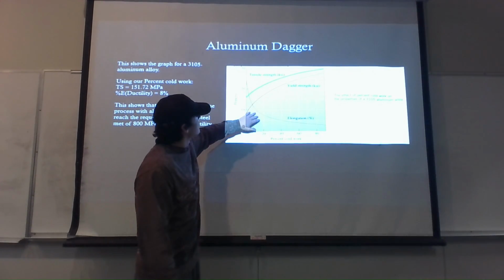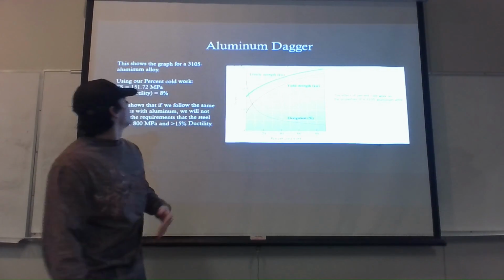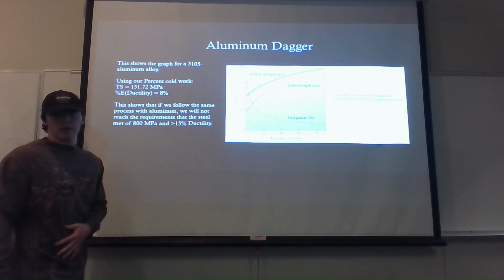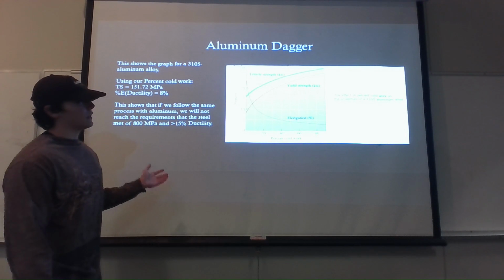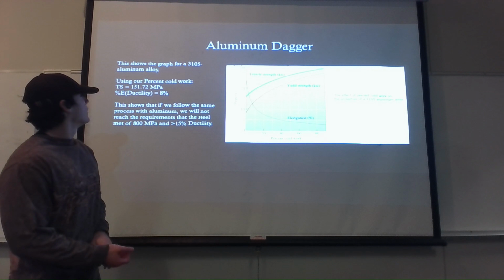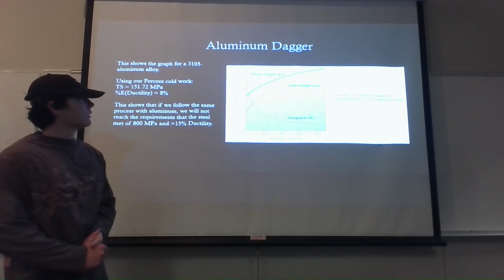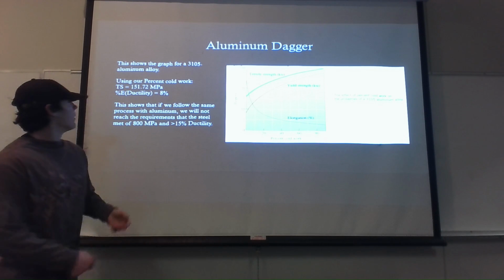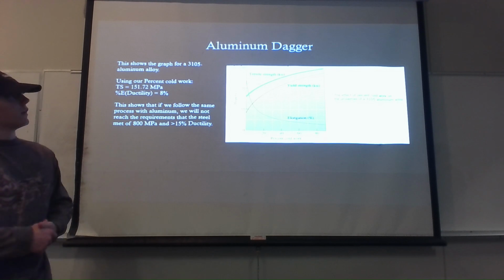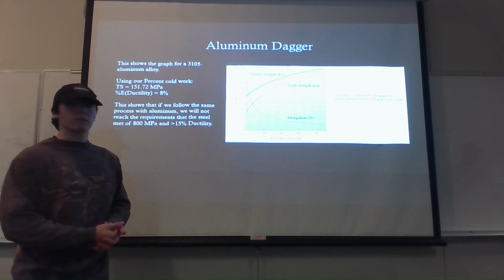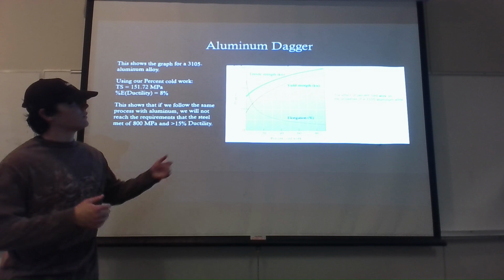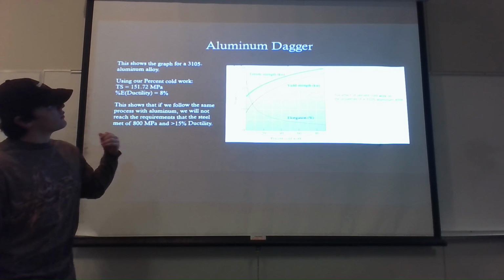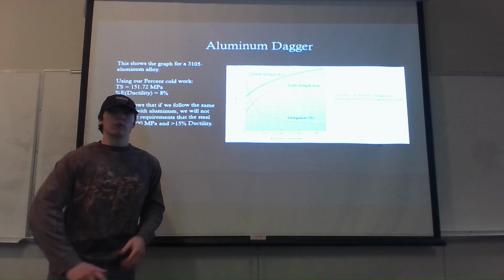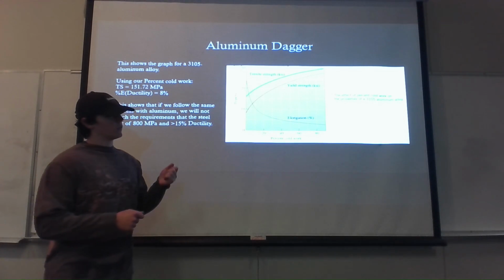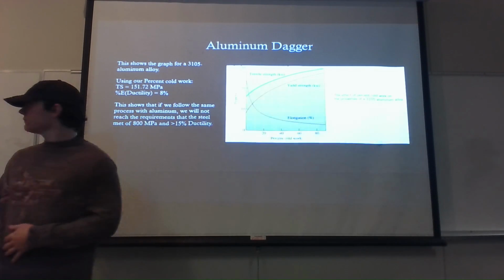And then if we take that 13 and keep following it up to the tensile strength, we'll only get around 151 megapascals. So this is a lot less than the 800 we needed for the steel, and then the 8% is also a lot less for the ductility we needed from the steel. So this just shows that the aluminum has a lot different properties than steel. If you try to do the same process, your dagger is going to be a lot weaker, and it won't do as well as the steel would.